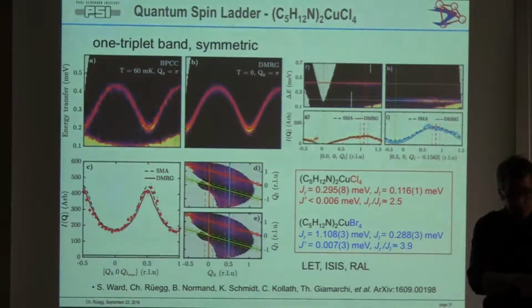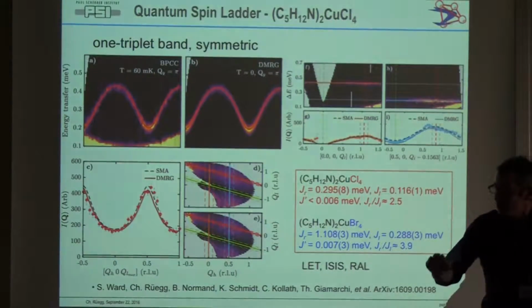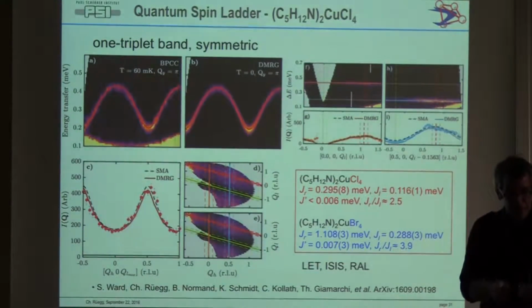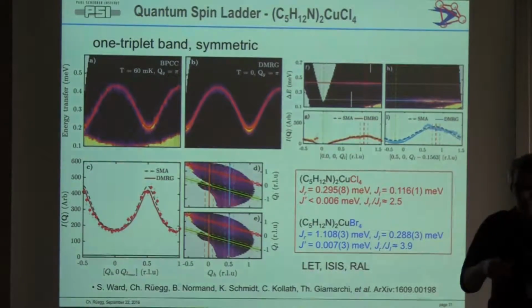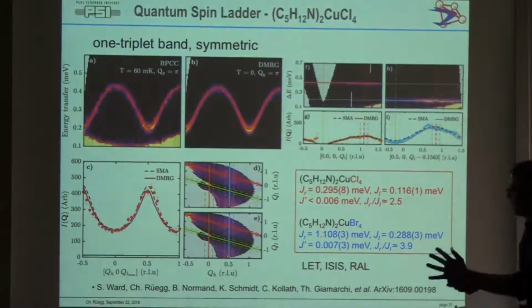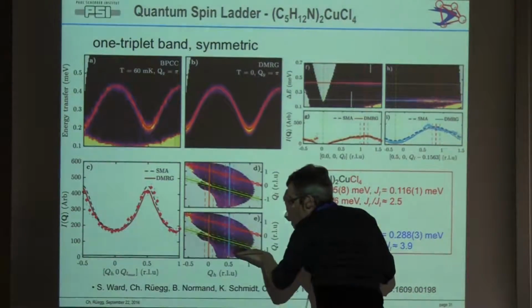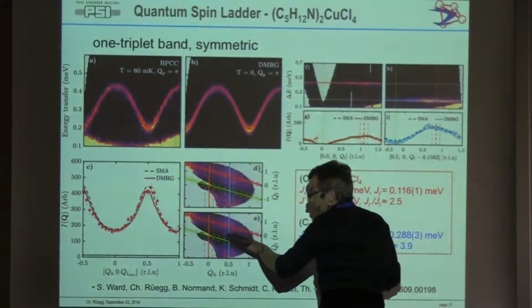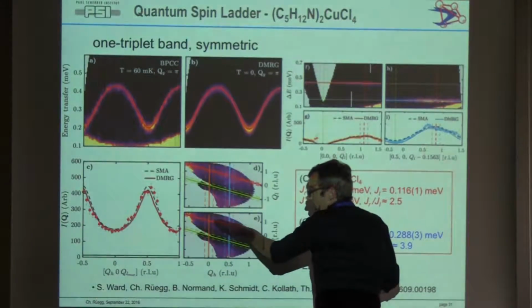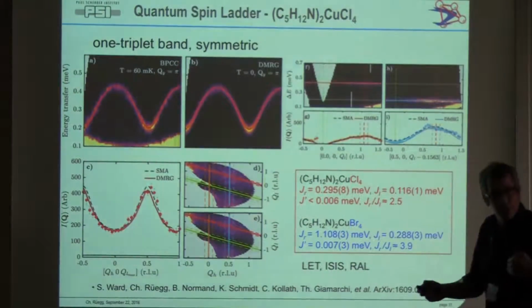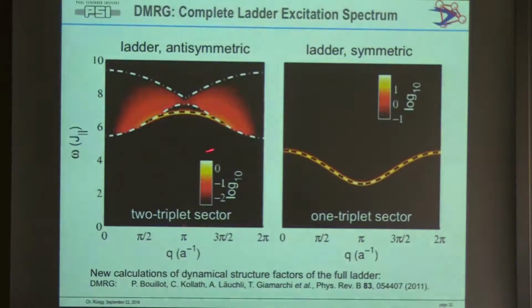The ladder has a rung, and it's not only the momentum along the ladder which counts, but if you go transverse, you also have the transverse selection. And this gives you a very powerful way by symmetry to select if you excite a 1 magnon or a 2 magnon excitation. And this exactly we can do. We can cut through momentum space to see only the 1 magnon excitation. You see here, if we cut at a different transverse Q momentum, you will see only the 2 magnon sector.